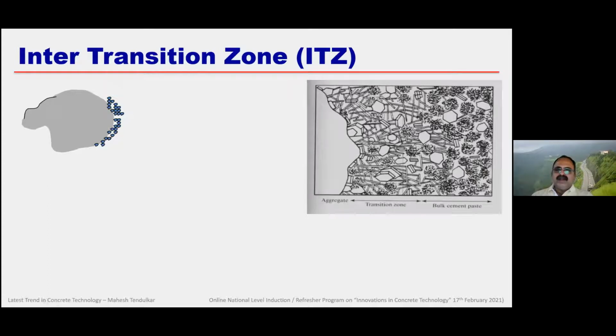So here, along with the aggregate, this is the hydrated product of cement. These are the hydrated products of cement and this is the aggregate. Along the aggregate, the weak calcium hydroxide will accumulate in this weak zone. That's why whenever we test our concrete in a cube test, we always find a failure of bond strength. This failure is mainly because of accumulation of calcium hydroxide in this transition zone.